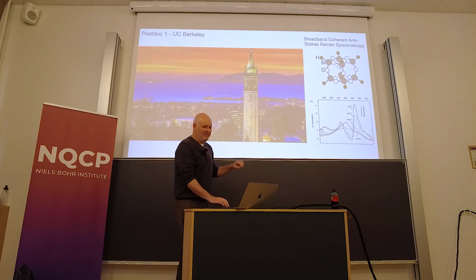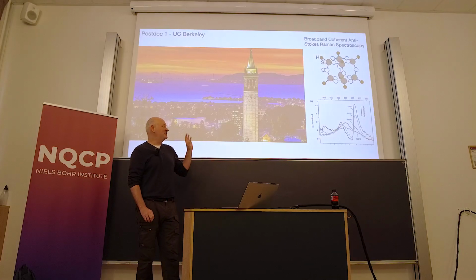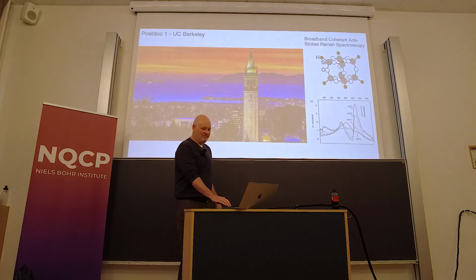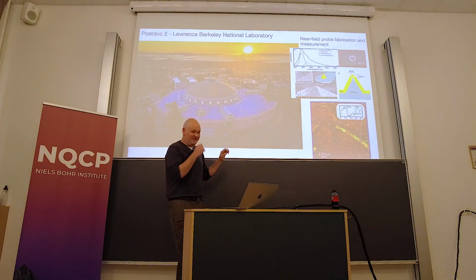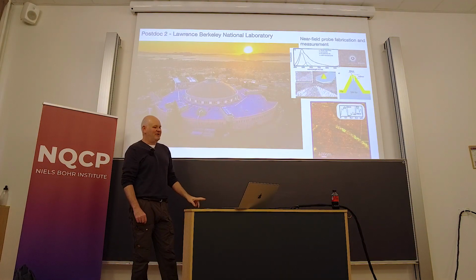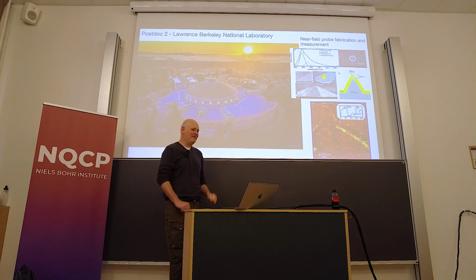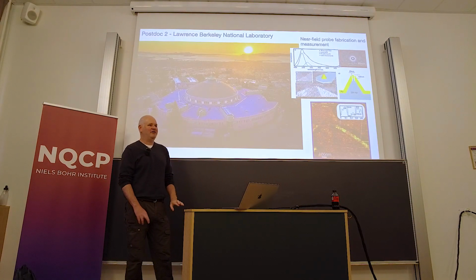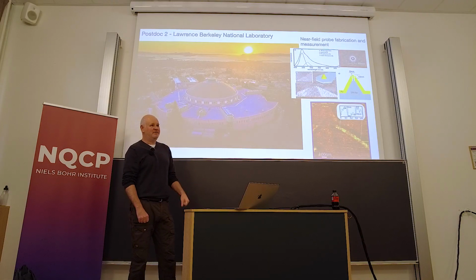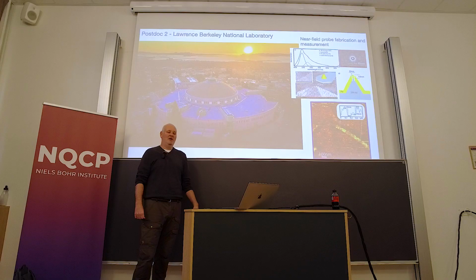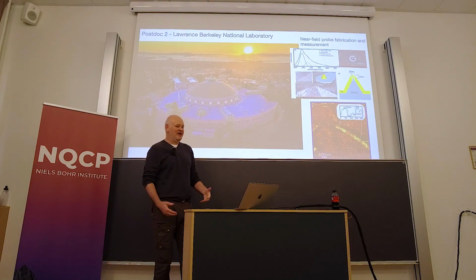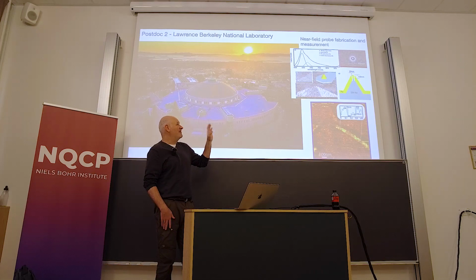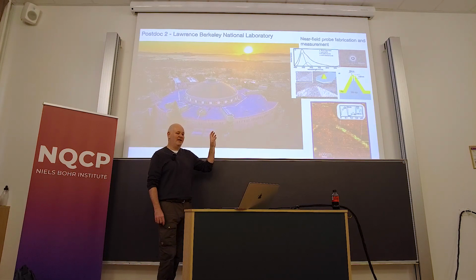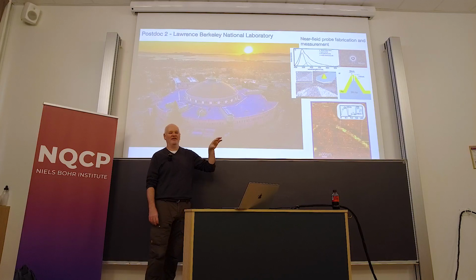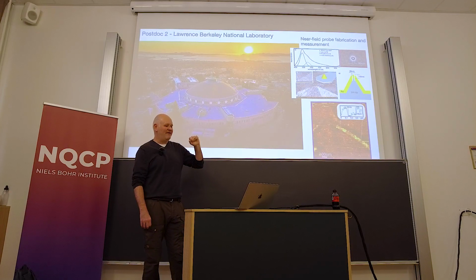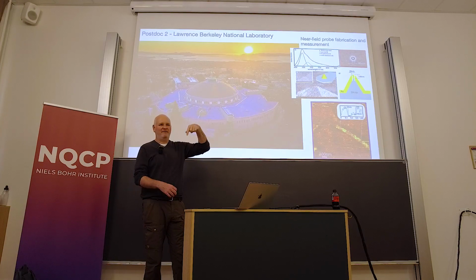So from that, where I basically spent my entire time in a dark laser lab just shooting very short pulses and mostly blowing things up, I moved just up the hill to Lawrence Berkeley National Labs for my second postdoc, where I completely changed directions and went to fabrication and use of near-field probes. So again, going back to plasmonic materials, but this time doing actual fabrication. I've shown an example here, but this is just one out of many where we actually take a near-field tip, or in this case, just a silicon nitride AFM cantilever, coat it with gold, and then use a FIB to put a plasmonic feature into that.